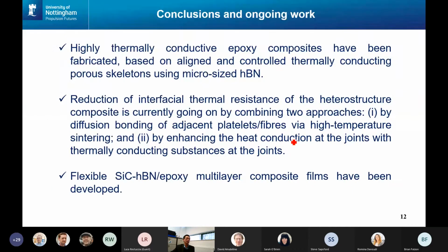So here are the conclusions on two different types of thermally conductive materials that have been developed. The main story is to try to reduce the interfacial thermal resistance of these kinds of porous structures, either by the sintering method or by adding additional thermally conducting substance at the joint positions.